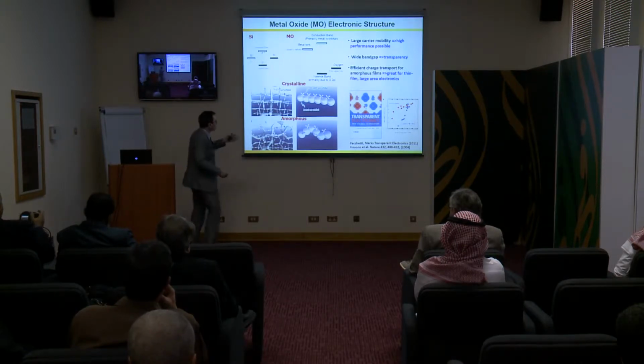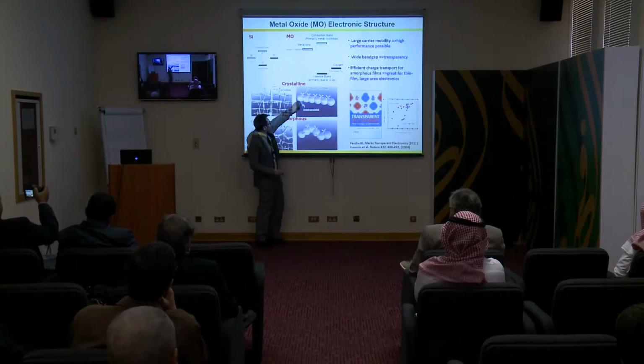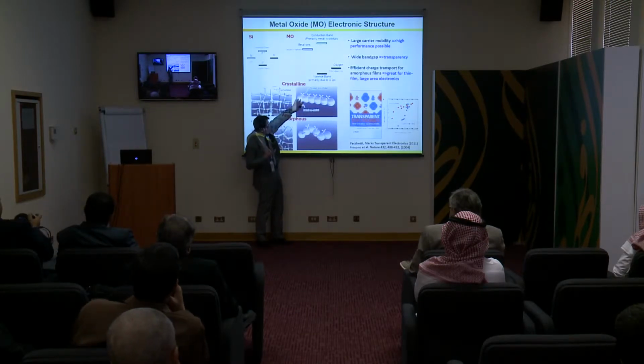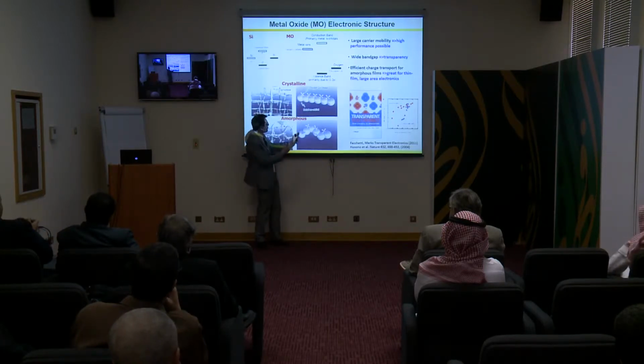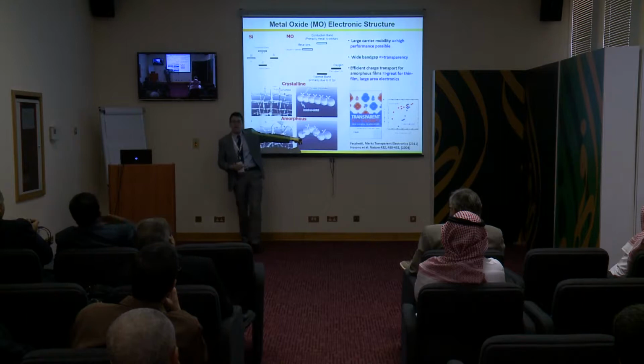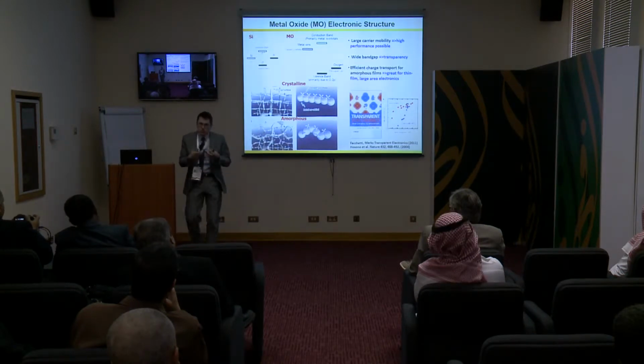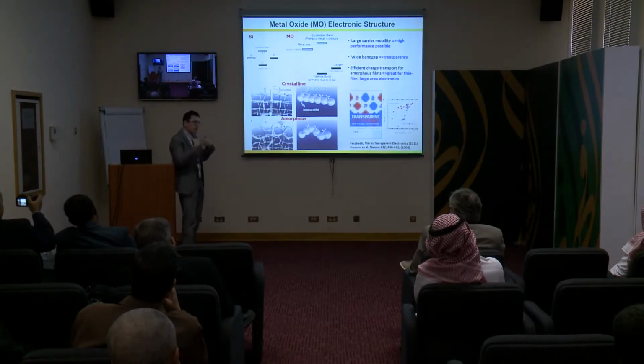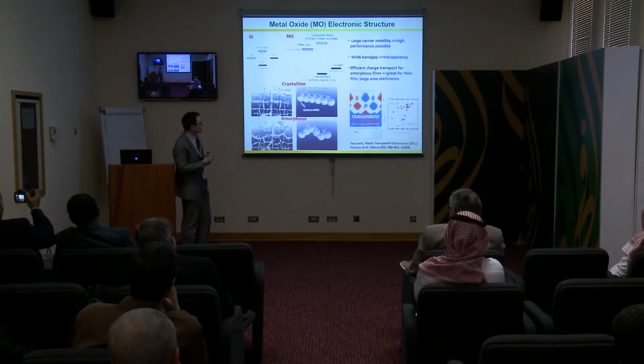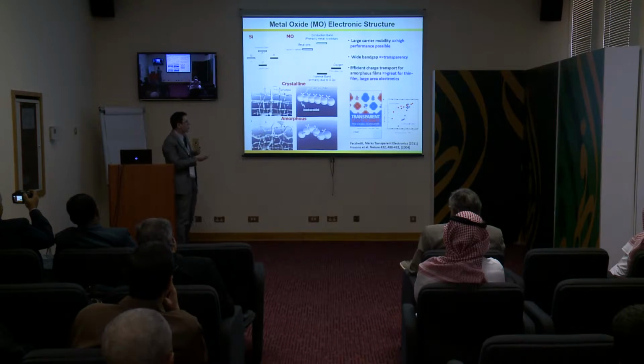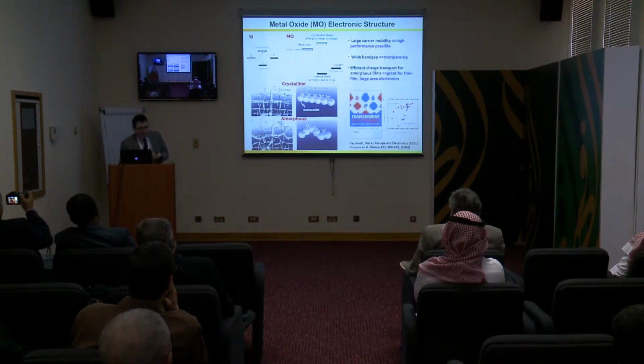And the reason is because for metal oxides, the conduction band is s metal orbital based. So no matter if you have a perfect lattice or if you have a distorted lattice, this spherical orbital provides a good path for electrons. Okay, so this is why it's very important in terms of a vision of printing electronics. Also, metal oxides can be optically transparent, so they can have also other advantages.